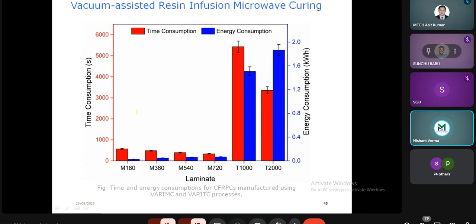vacuum resin molding, and in case of the conventional. So here we have taken the microwave power at 180 watt, 360 watt, 540 watt, and 720 watt. And you can see how much less time is consumed in case of the microwave compared to when we used the conventional heating technique.